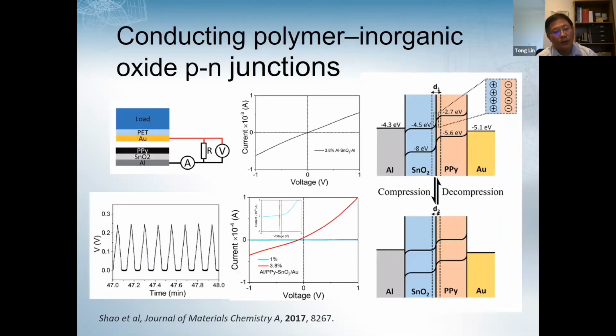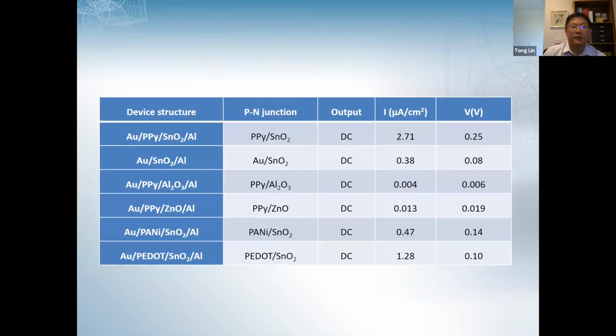Not only Schottky junctions, we've also found that if a conducting polymer can form a p-n junction with another semiconductor, like an inorganic oxide, the p-n junction can also be used as a generator. Here is an example. We use tin oxide and PPy to form a p-n junction, because tin oxide is an n-type semiconductor. The device can generate a DC power on compression. The voltage output is around 0.25 volt. The principle is very similar to the Schottky junctions. Here are more results from different p-n junctions. You can see the voltage output varies depending on the semiconductor material used.